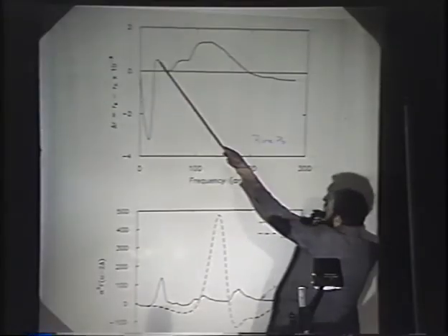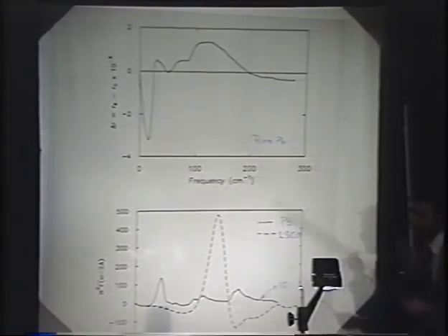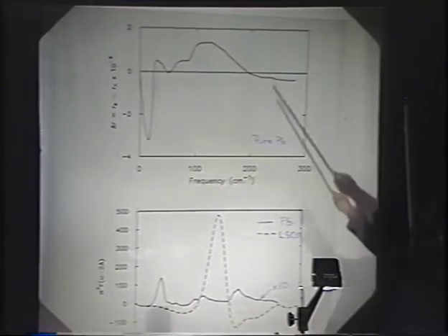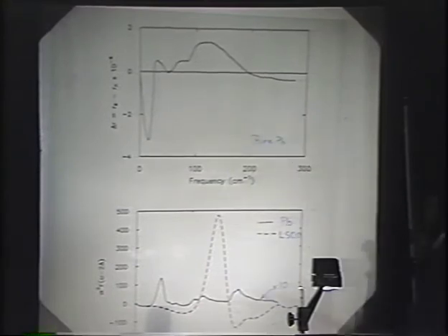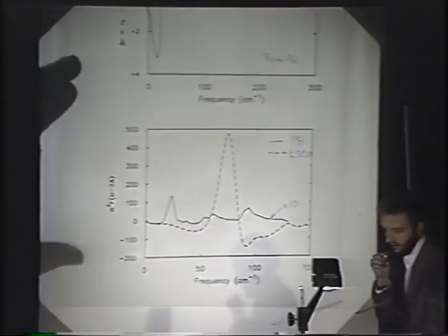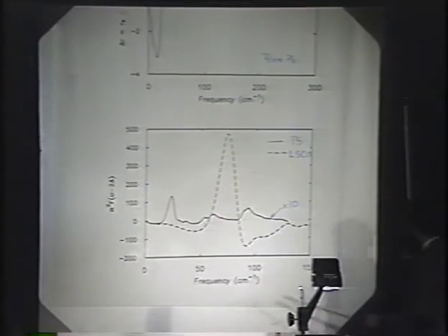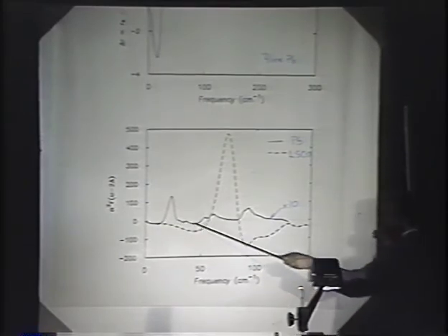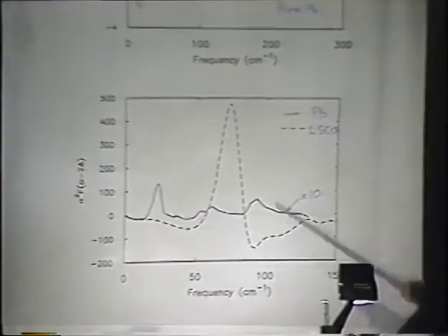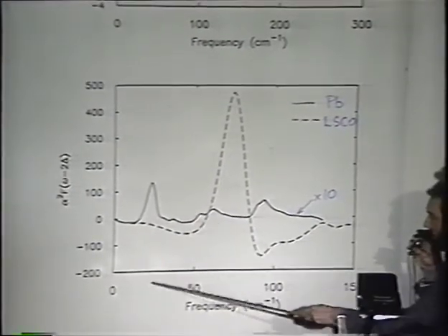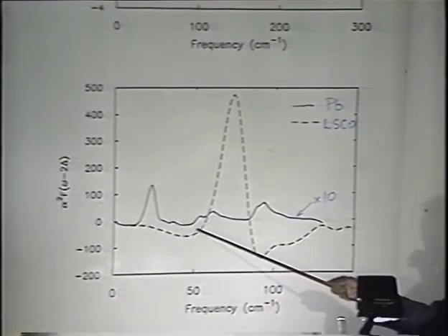Now, if we look at, say, the difference in surface resistance for pure lead, you can see that it's got this interesting structure here. And this is just the phonons coming into the determination of the surface resistance. The first derivative of this is roughly proportional to the alpha squared F, the electron-phonon coupling. And for the pure lead, you get the solid curve multiplied by 10 times, just so you can see it on the same scale. So there's the large elastic peak at 2 delta due to impurity scattering, and then the phonon structure for pure lead.